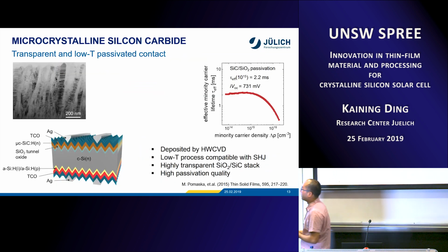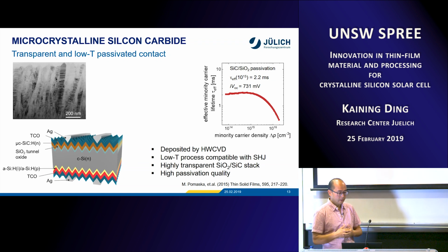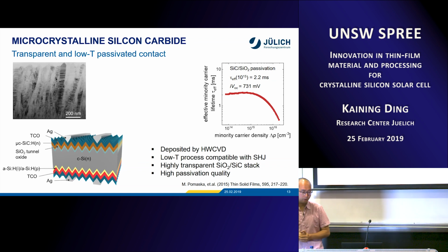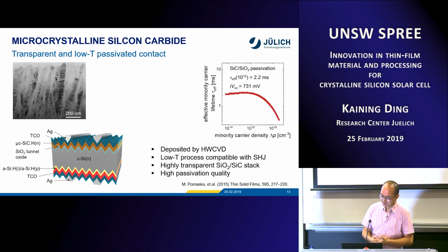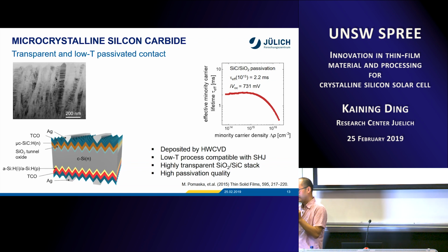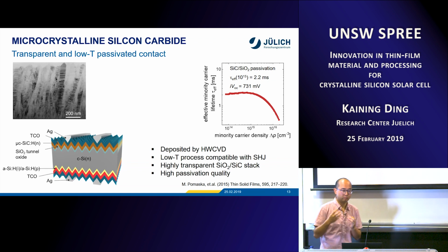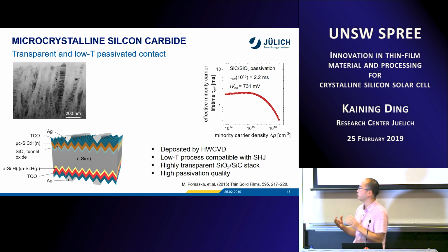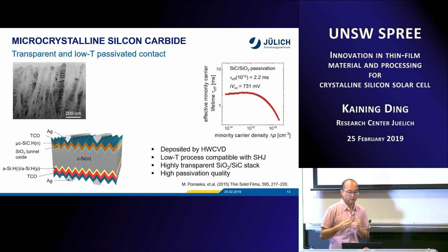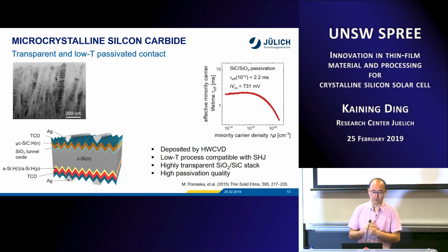Okay, so that's about nanocrystalline silicon oxide. The next material that I want to introduce is microcrystalline silicon carbide. We call it our magic material. It is grown by hot wire CVD, where you dissociate your precursor gases at a hot wire up to 1800 or 2000 degrees C, and the dissociated radicals come to the surface and form a film.